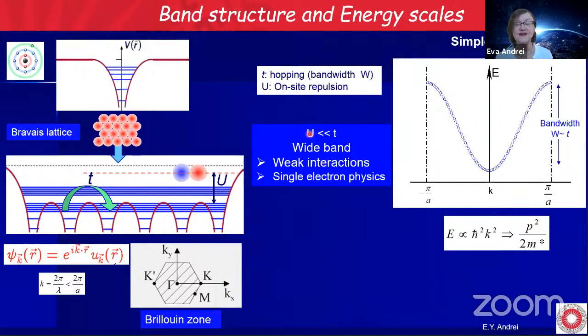When the on-site repulsion is much smaller than the kinetic energy, we have a wide band. The interactions between electrons are very weak. They hardly see each other, and we get single-electron physics. The energy is proportional to the square of the momentum, like for a classical particle. The prefactor here we call m star. This is where we hide all our ignorance about what the lattice does to the electrons, and we call it an effective mass. If the interactions are very weak, this m star is equal to the electron mass, but of course this changes a lot when the interaction is strong. So now I can throw in a bunch of electrons, as many electrons as are allowed by these atoms, and the highest momentum is the Fermi